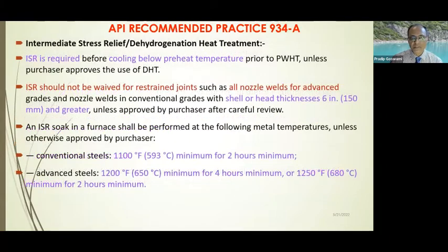And intermediate stress relief, or ISR, is required before cooling below the preheat temperature. That means prior to post-weld heat treatment. And what happens is that following fabrication, the welds undergo an immediate ISR.